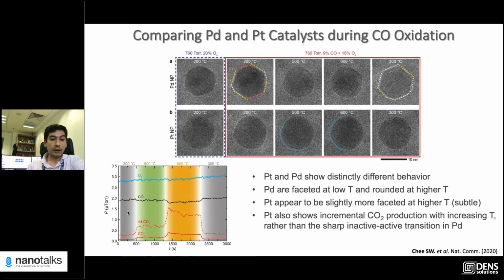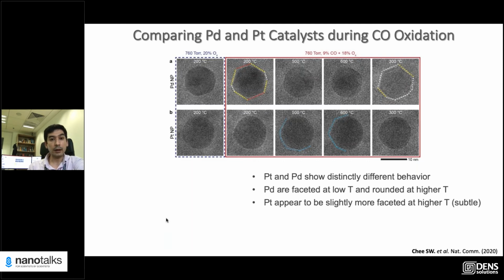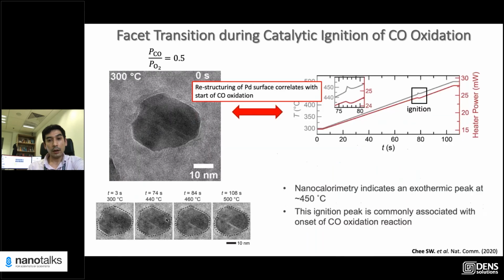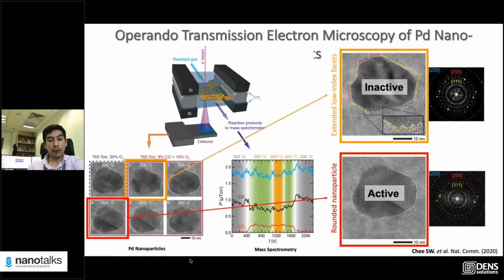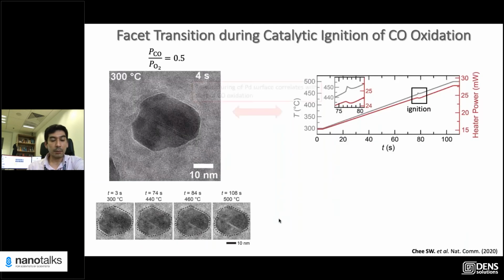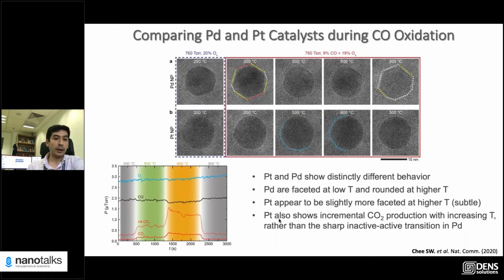And this is actually multiplied by 4 times. Of course, if you increase the temperature, the activity increases. So we multiplied by 4 just to exaggerate. Otherwise, it's really hard to see what's going on. If you go back here, you go on state and you're fully on, right? And if you increase temperature from 500 to 600, there is no noticeable change. In the platinum, the change is very small, and it scales with the temperature, which already suggests that the platinum is not very catalytically active for this CO conversion reaction in this system.